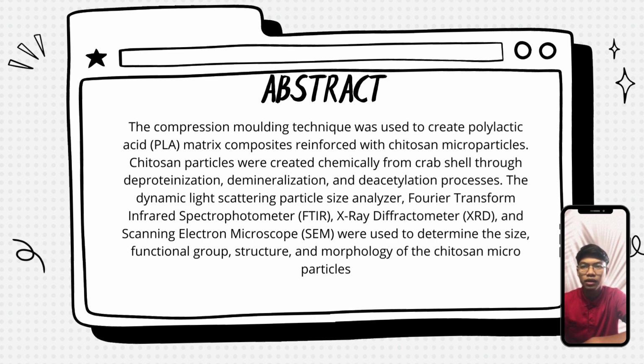The result revealed that the mechanical and wear properties of the developed PLA chitosan composite have improved. The optimum value for mechanical properties was found to be 6% Chitosan particle reinforcement, and 10% for wear resistance. The scanning electron microscopy examination of the composite revealed that particles were distributed uniformly at lower weight fraction, while particle clusters appeared in the same image at higher weight fraction.